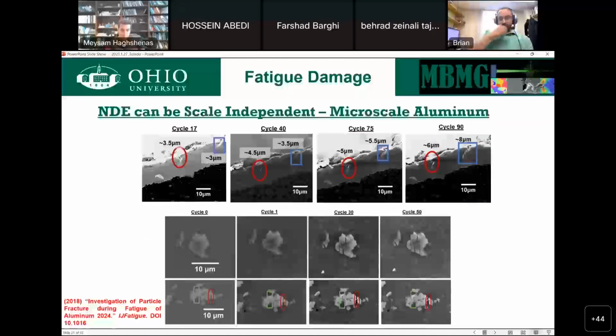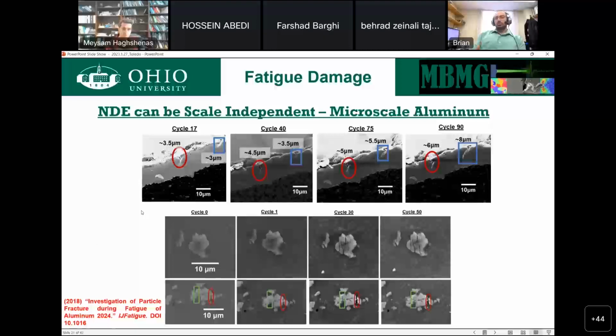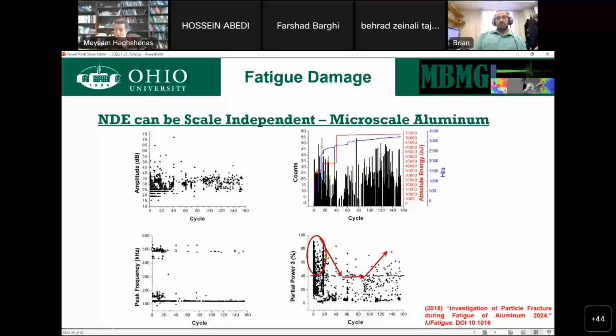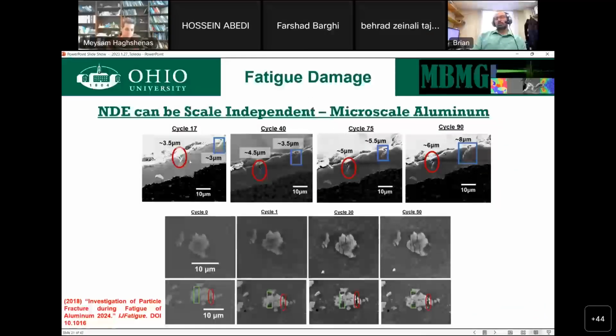Now, we can also prove this by looking at that response and then going around and searching the structure to try to figure out where the defects happened. So in some cases, we can observe particles and see them as we apply cycles, see them actually fracturing as they grow and how that grows. In other cases, like the case where we start to see a change, we don't have these 500 kilohertz anymore. It seems to have reduced in content. We can actually map that to when a crack starts to grow, a macro crack from the edge of the sample. So the methodology works at that small scale.